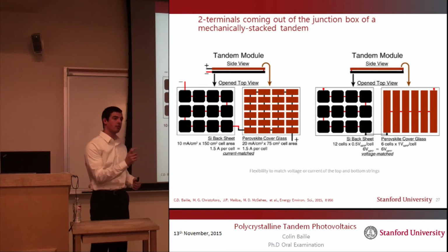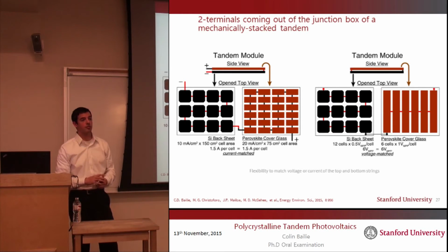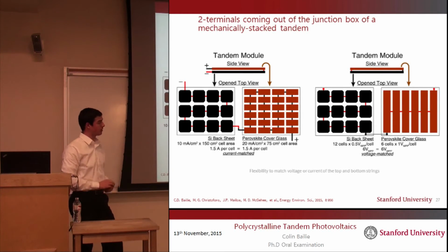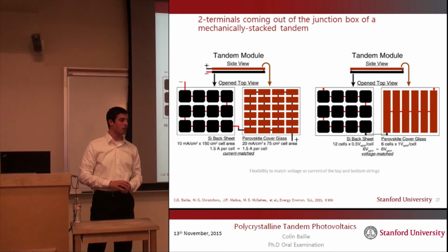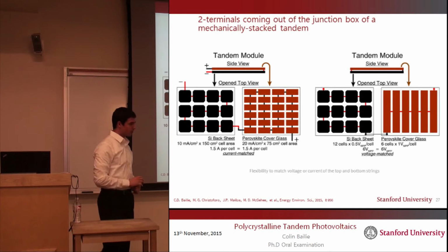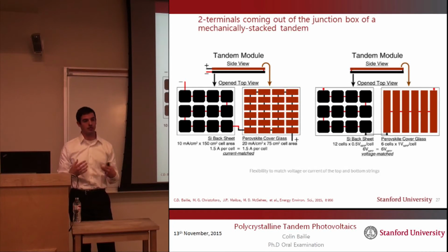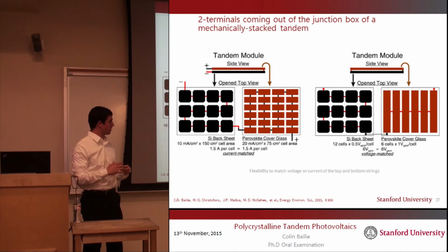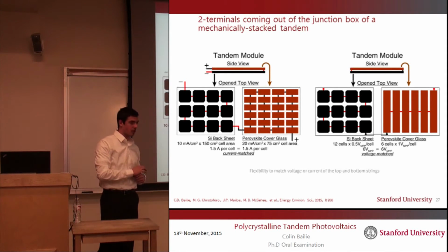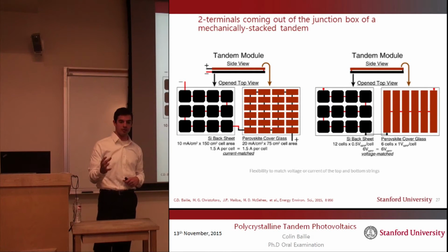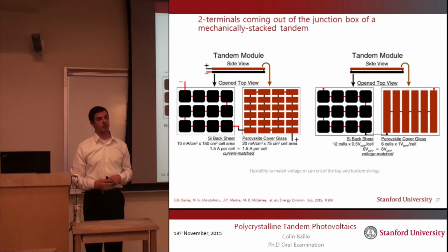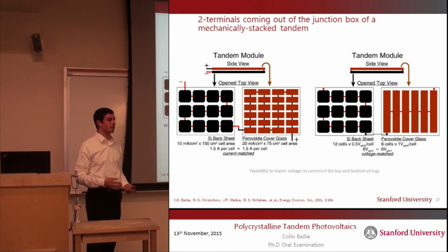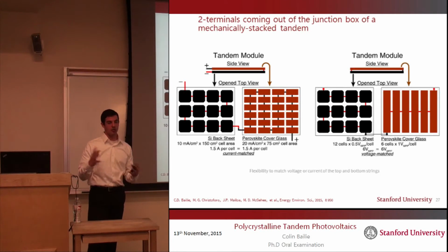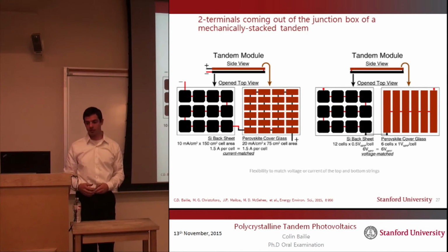So maybe the voltage of the silicon changes much more than the voltage of the perovskite as you heat it up or cool it down. And so the third option is to throw in some power electronics. If you throw in some power electronics, then you can string up the cells however you might like, and this extra electronic circuit that you added in would correct for any mismatches that you might experience when you put this out in the field.